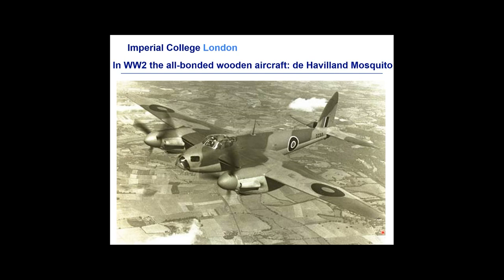The glue was actually sufficiently strong and tough at first for the de Havilland Mosquito, but degraded when it was exposed to hot, wet climates and then completely lost its strength. So when the Mosquito aircraft were sent to the Far East in the very hot and wet climates there, they quickly started to fall apart. But we engineers are very innovative, and the maintenance engineers would put their heads into the wings of the Mosquito and smell. And if they smelt something like very old camembert cheese, they knew to take the plane out of service. So a very early form of a non-destructive test.